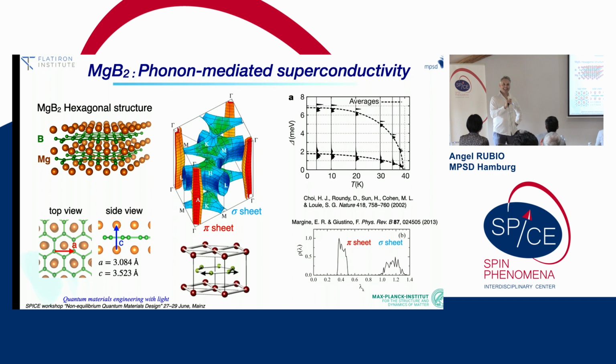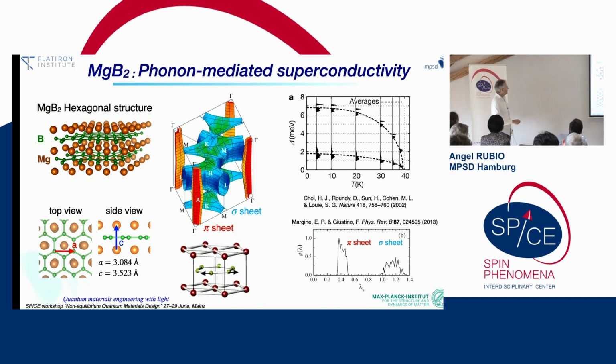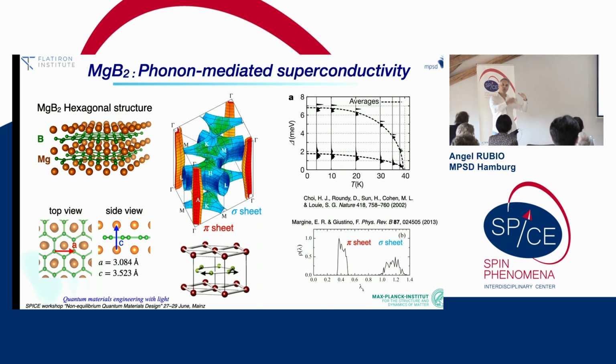It is the prototype of an electron-phonon mediated superconductor. At least on that, there is no doubt that electron-electron correlations play a marginal role, besides what you capture at the LDA level. This is good because the theory reproduces magnesium diboride very well outside the cavity. Also, we know exactly which phonon modes do the nesting between the sheets, which are the optical phonon modes. Then the question is, what happens if I put magnesium diboride in a cavity and look as a function of the light-matter coupling?